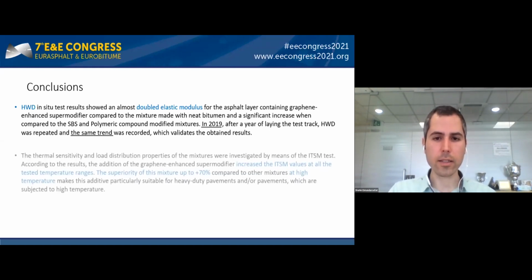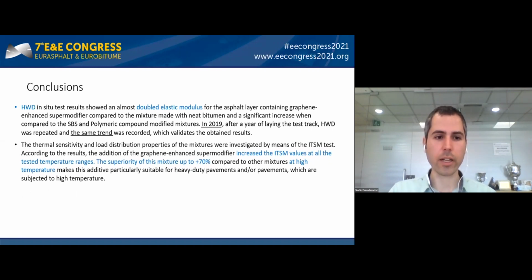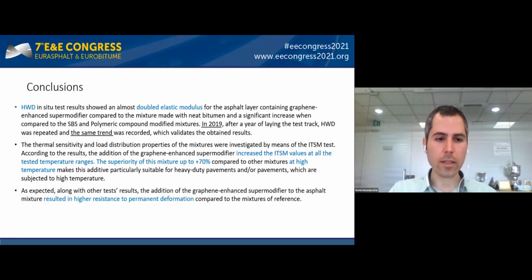Here, in this early stage trial section, HWD test results have been obtained, and according to the test results, we have seen almost double modulus for the mixture containing the graphene enhanced asphalt modifier. The thermosensitivity of the mixtures was investigated by means of ITSM modulus, and as seen in the HWD investigations, the mixture containing super modifier showed a significantly higher modulus when compared to the other 3 tested mixtures.